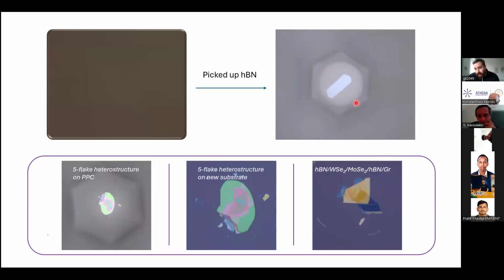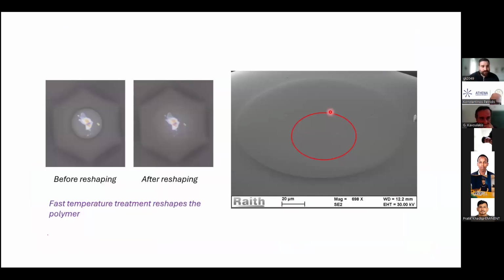You will see now here a ring appears on this image. This is basically because the polymer, when it cools down, creates this effect. It shapes in this geometry. If the flake is smaller, it cannot affect it. But if it's bigger, or if the next flake that you want to pick up and create your heterostructure is bigger, it might create some local strain. So what we have to do is take out the glass, go to a hot plate for 1 minute at 70 degrees, heat it up, the polymer will reshape, will reflow, and it will become smooth again. And then we go for the next pickup.